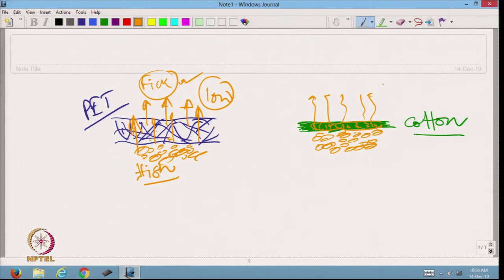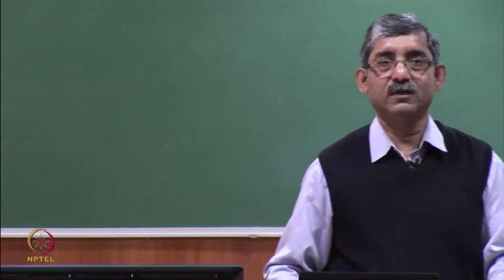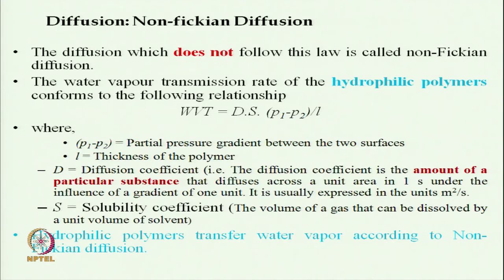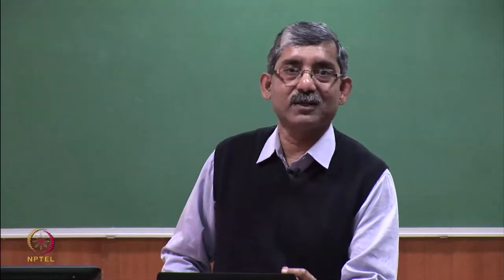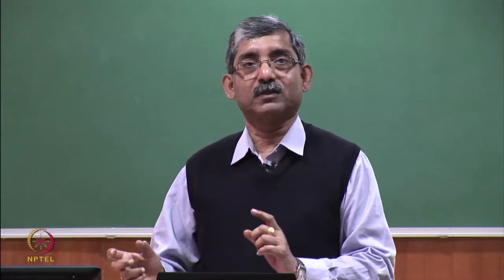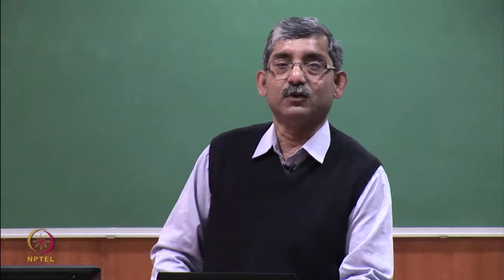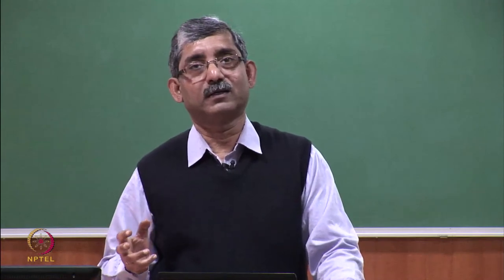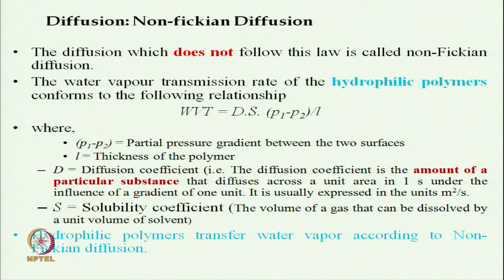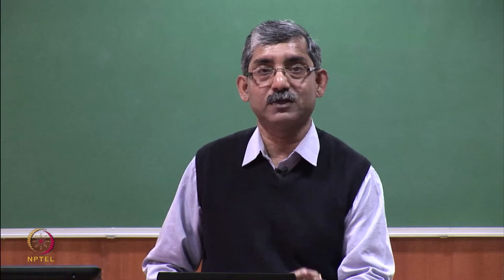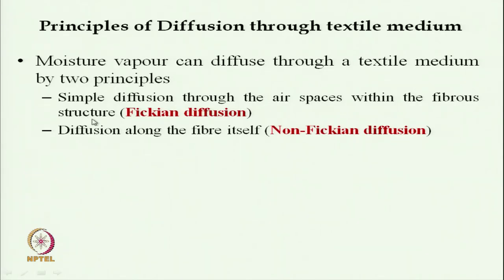So, this diffusion is known as non-Fickian diffusion. So, both are diffusions, but the Fickian diffusion is through the pores, air pockets, and non-Fickian diffusions are through the material. Now, as far as textile materials are concerned, say sports textiles, both the Fickian and non-Fickian diffusions take place. So, if we use a hydrophobic polymer, in those polymers it is mainly Fickian diffusion. So, moisture vapor is transmitted through Fickian and non-Fickian diffusion, and normally they take place together depending on the structure.